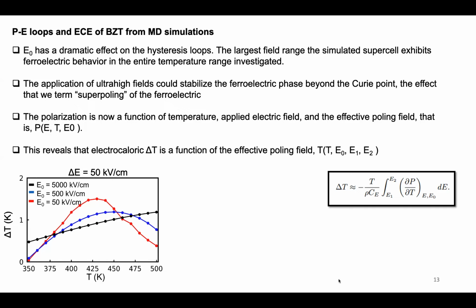So the applied field is 50 kilovolts per centimeter. For the constant applied field, for the different poled samples, we get a different electrocaloric change in the temperature. So what it means here is that the polarization is now not only a function of field and temperature, it's also a function of the poling field, that's E naught, the amplitude of the field. And eventually, the electrocaloric change in the temperature also becomes a function of the amplitude of the field.